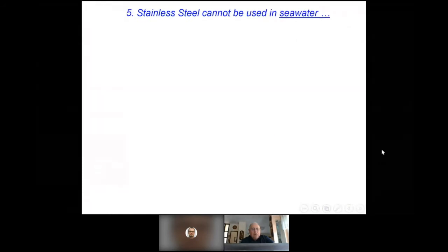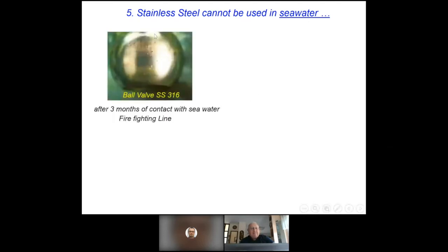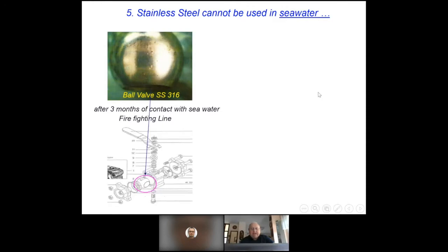If you open old textbooks on corrosion 20-30 years ago, you can read that stainless steel cannot be used in seawater. Really, at the beginning of the 1990s, one engineer at our oil refinery showed me a ball valve made from stainless steel 316 that was mounted in the firefighting line containing Mediterranean seawater and failed because of leakage. This ball valve, you see, served only 3 months. Pitting corrosion occurred exactly according to the textbook.